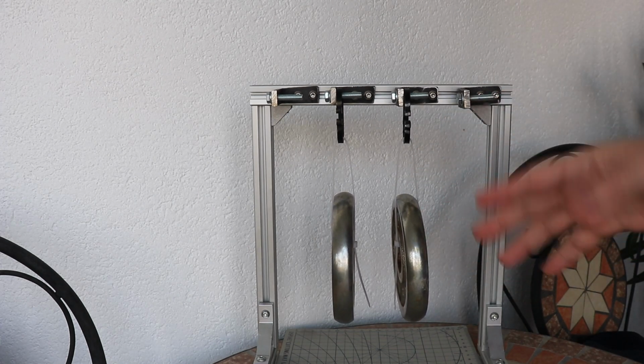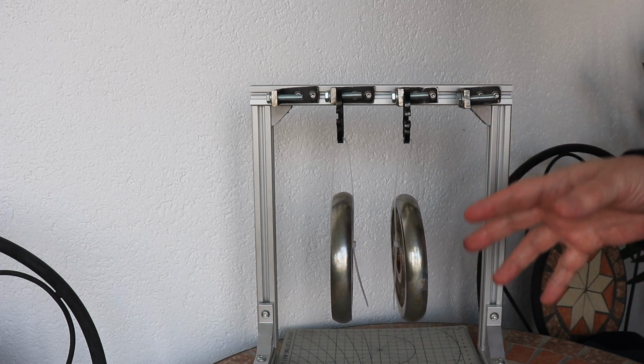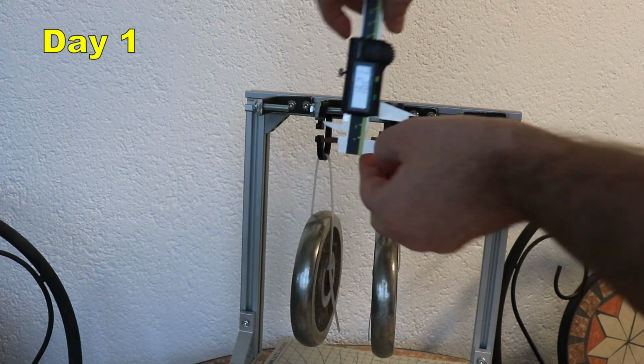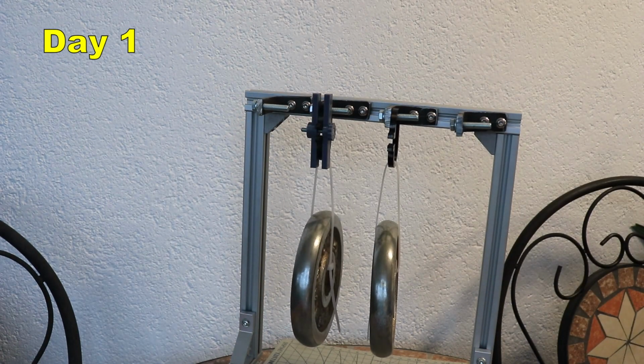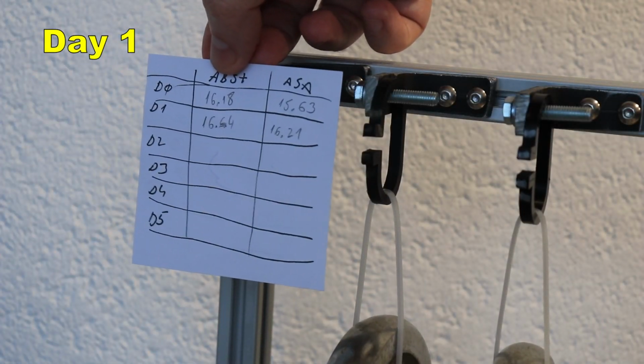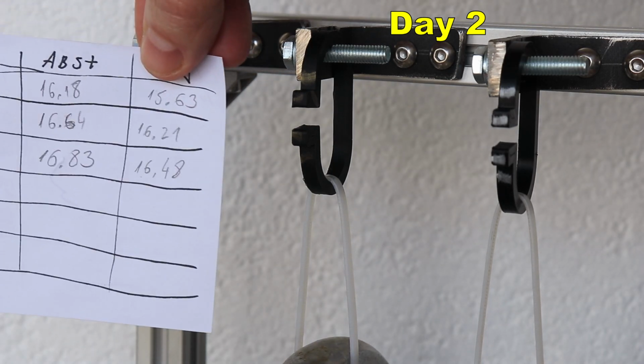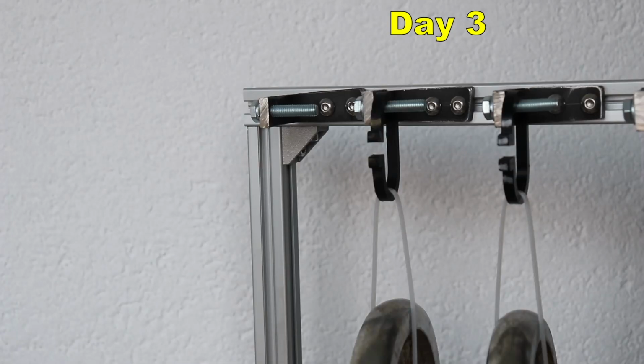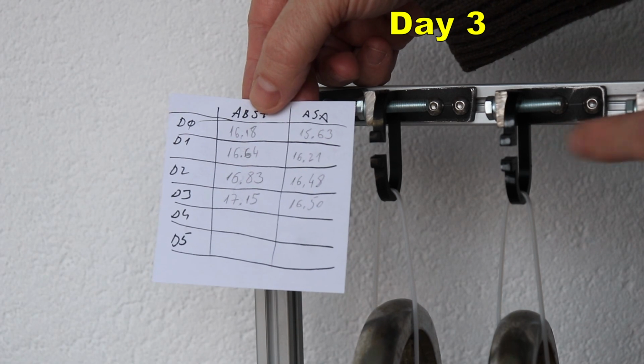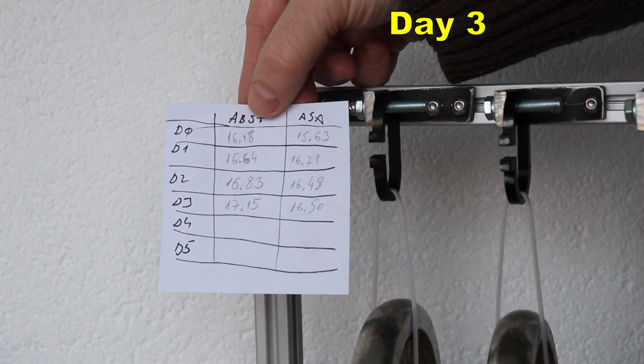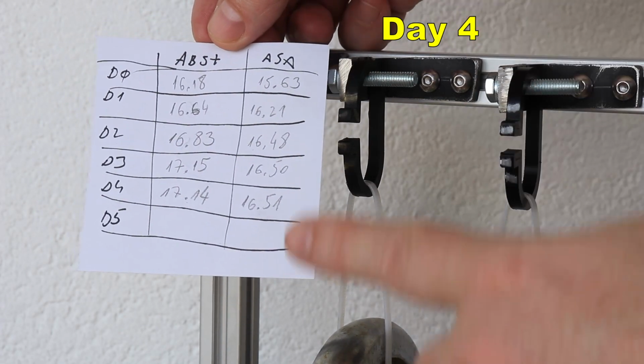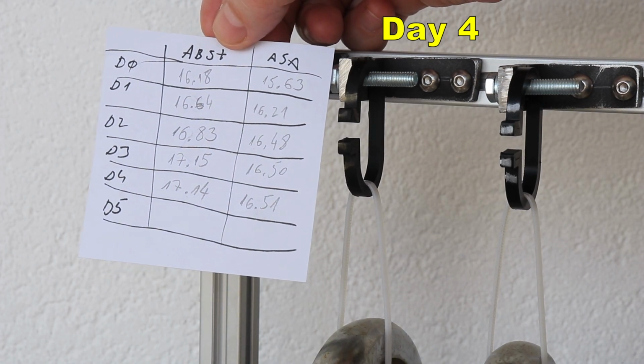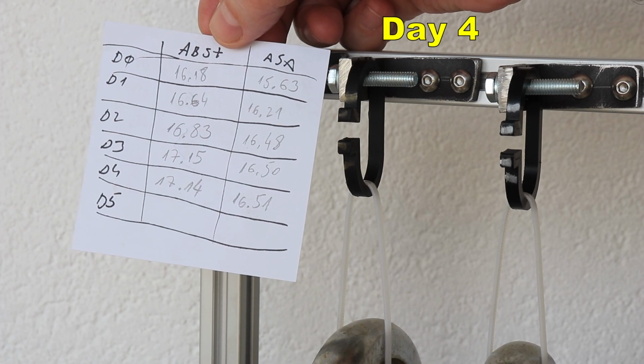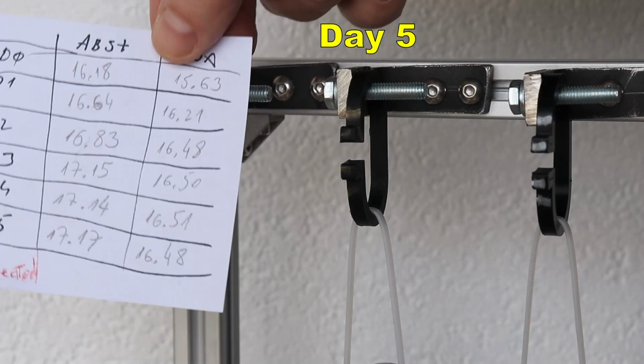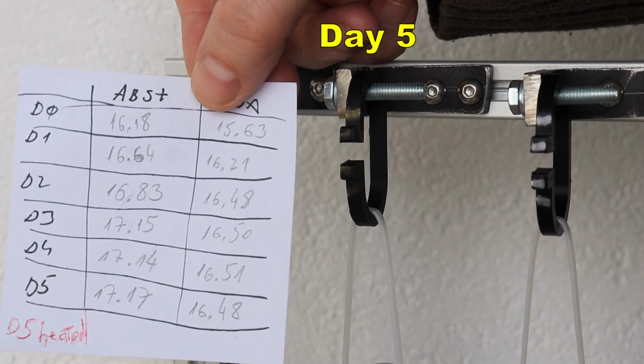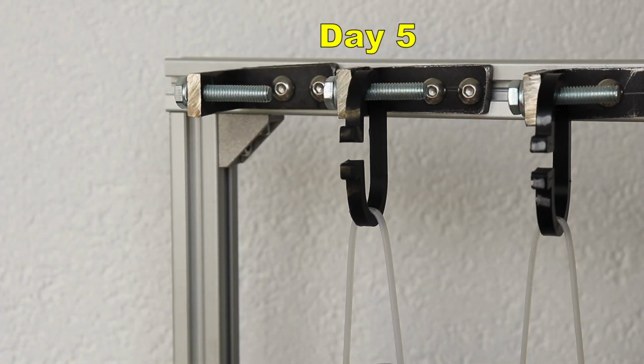And I will repeat this every day, and on the last day I will put it inside the enclosure at 45-50 degrees Celsius. ASA 16.21, ABS Plus 16.64. So this is the state after one day. I already measured it, so these are the dimensions on day 2. And this is day 3, basically almost no changes on the ASA test object, but very minimal on ABS Plus. Day 4, and these are the numbers. For ABS, I got even a little bit smaller value, but very minimal, so this must be inaccuracy in measuring, but basically the creeping completely stops in both cases. And this is day 5, basically no significant differences, so the creeping has stopped completely. And now it goes to the heated enclosure and then the final conclusions.